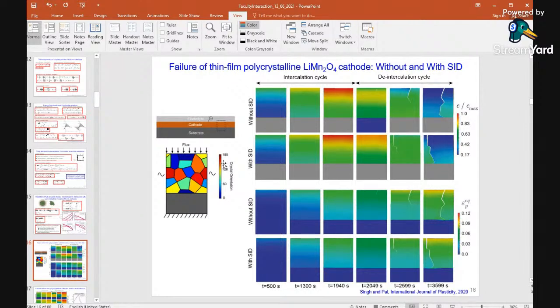So in the first case, we take this microstructure, we put a periodic boundary condition. So you can consider the entire thin, like an infinite layer, and we put the crystal orientation, and then we do the intercalation from the top, and we take care of the mechanical stresses in two cases, with mechanical stress and without mechanical stress. So what is happening? First we do the intercalation, and then we de-intercalate. In the intercalation, first we see the concentration. We have the plot for the concentration of the lithium ions, which is coming from the top, and then we de-intercalate, and during de-intercalation you see the crack develops.